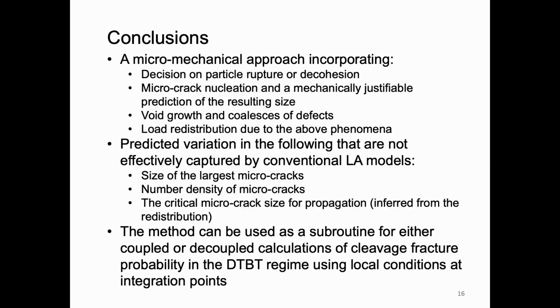So to the conclusions, we have presented this micromechanical model, which can predict the size of the largest microcracks, the number density of microcracks, and the critical microcrack size for propagation. And the idea is that it can be used as a subroutine for either coupled models similar to GTN or decoupled calculations of a probability of cleavage. Thank you very much.